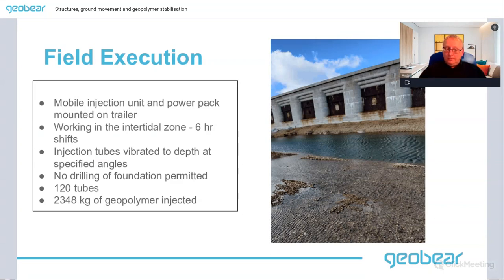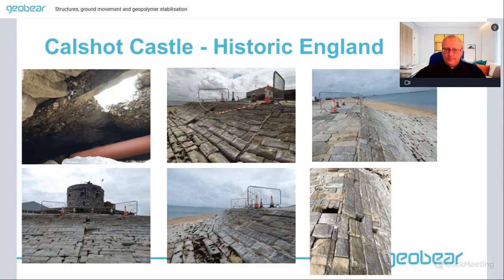It was done using a mobile injection unit and power unit. We had to work in between the tides because at high tides our injection locations were underwater, and so I think we did 120 tubes and 2.348 tons of polymer were put in, and it completely stabilized that structure with no further movement.